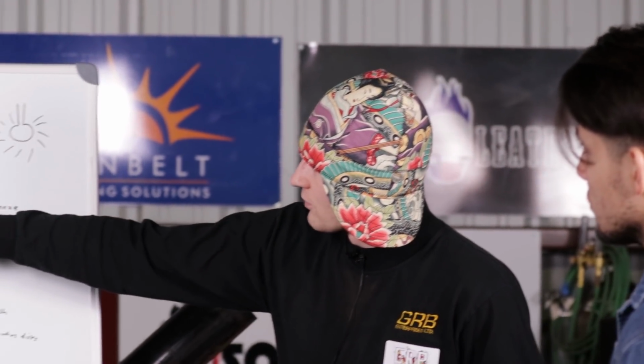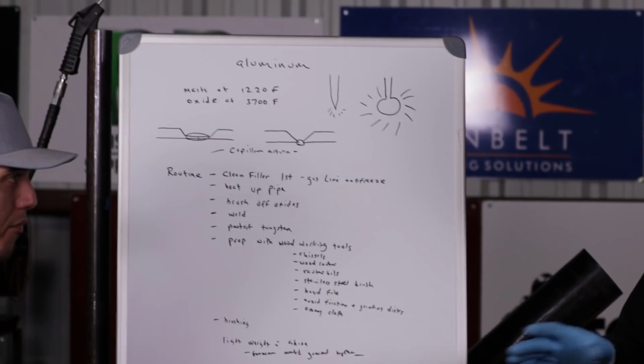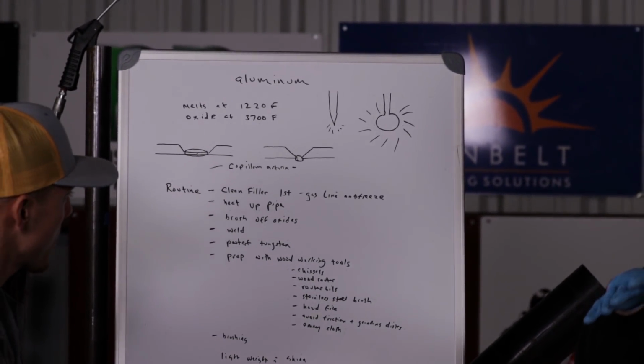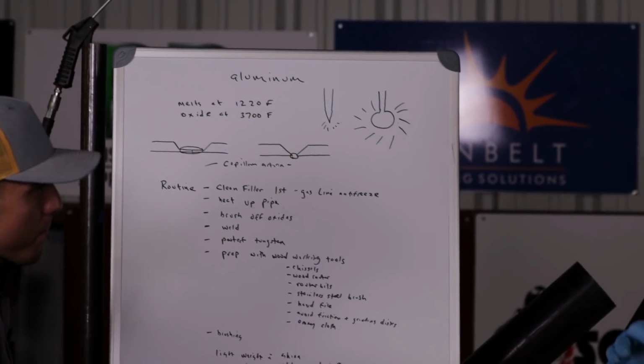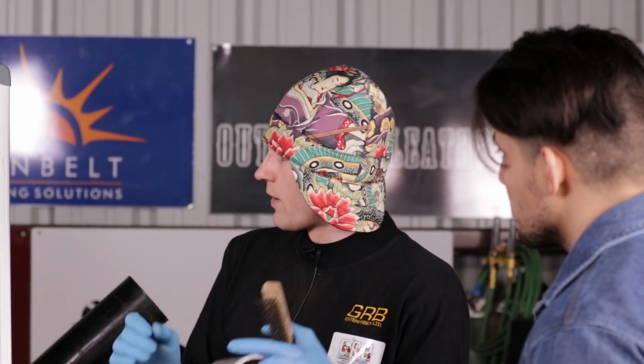Usually if you wear a shade 11 lens, it helps with removing the gloss and glare of the weld puddle. If you use a shade 11 lens, you can give a surge of current. It'll remove a lot of the cleaning action. You'll see the weld puddle. It'll melt the seam in the middle and form a weld puddle. And then you'll see it go slightly concave. When it goes concave, you can just dab into the weld puddle, and then you'll see it kind of grow. Then you move to a leading edge, and repeat the process all over again.